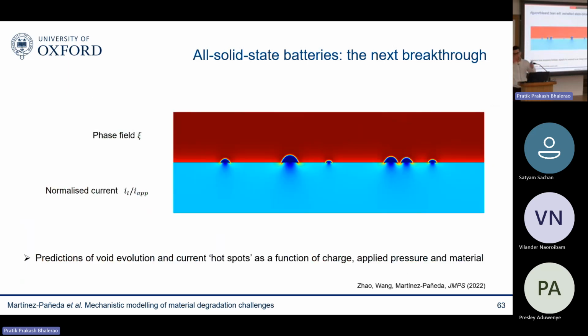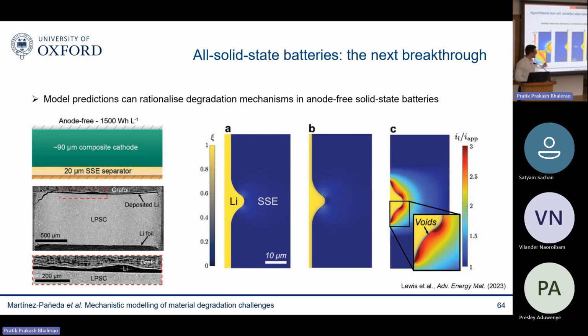And now what we're doing is looking at more realistic cases. So we apply a pressure. We see what pressures we need to enable a solid-state battery breakthrough. We put in multiple voids. We do multiple cycles of charge and discharge, and we also use this to test ideas, new interfaces, new cell geometries, and so on and so forth. And one last thing I'll say is that together with colleagues at Georgia Tech, we also look into what they call anode-free batteries, where you create your lithium metal anode by the first plating step. And we saw that, depending on how homogeneous that lithium plating step is, you get a very different behavior with the model. And they showed that later with experiments.